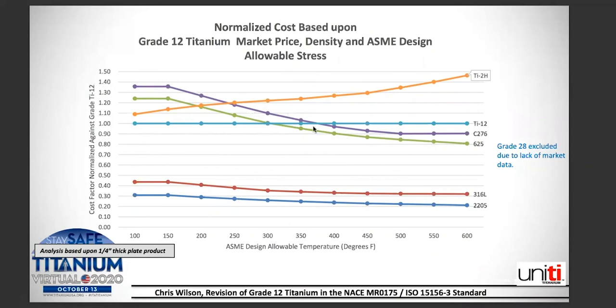Now, some of the other alloys, C276 and 625, you can see it changes as the temperature increases. Those materials become more competitive. But at lower temperatures, depending on the application, if the temperatures were 400 degrees and below, then grade 12 is certainly competitive, in some cases more competitive from a cost factor aspect.